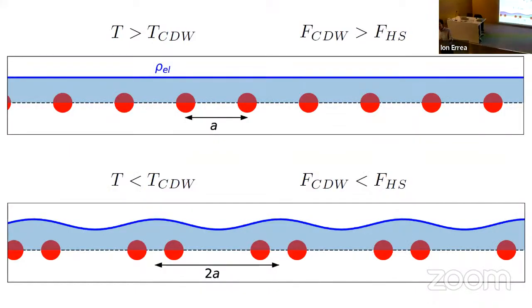This is the classical picture of a charge density wave. We have a lattice with this periodic repetition of atoms, and imagine this is a free electron gas, and the density is homogeneous. This is a picture at high temperature, above the charge density wave temperature. If this is a thermodynamic state, it means that above the charge density wave temperature, the free energy of the charge density wave phase is higher than the free energy of the high symmetry phase.